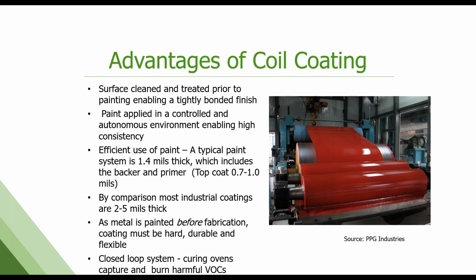This is a controlled environment, again, so we get reproducibility on color and film control. It's a closed loop system: the curing ovens capture and burn any VOCs that are in the paint system. We actually use that. Most lines use the VOC burning to refire and heat the ovens, so it's closed loop. So sustainability is very good. Next slide.